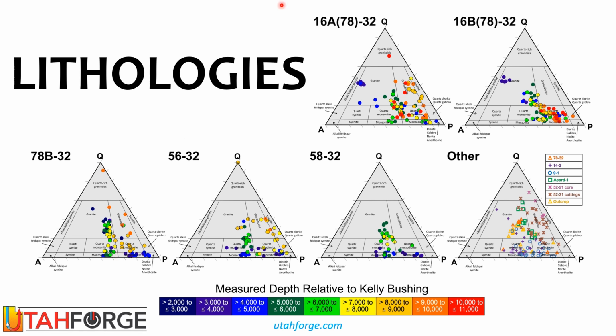So these symbols are color-coded by depth, going from shallow in purple to deep in red. There is a compositional shift away from the K feldspar corner at the deepest drilled levels that you can see in the orange and red points in 78B32, 5632, and 16A. If we look at 16A, our injection well, you can see that as we move deeper to depths below 8,000 feet, things shift out to the right.